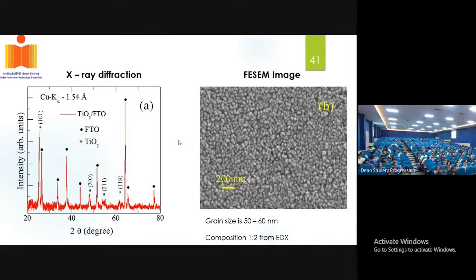So this is X-ray diffraction of the titanium dioxide material. We were able to get all the peaks that are relevant for the titanium dioxide. I would like to emphasize one point here: whenever you take any nanomaterial or any material, the first thing you need to do is check the structure of the material. In what structure has it formed, whether cubic, tetragonal, orthorhombic, rhombohedral, hexagonal, monoclinic or triclinic. First you confirm that, and then attribute your results to the structure.